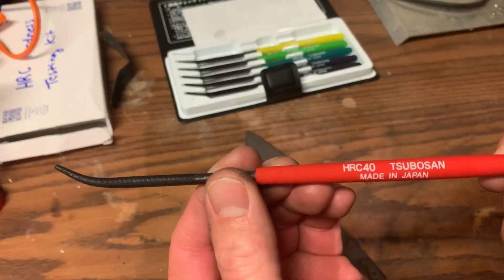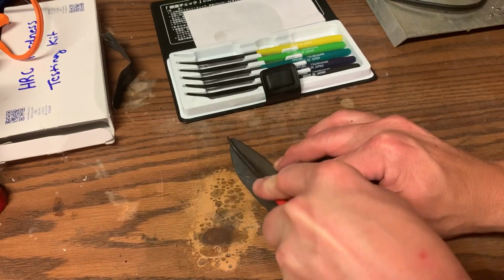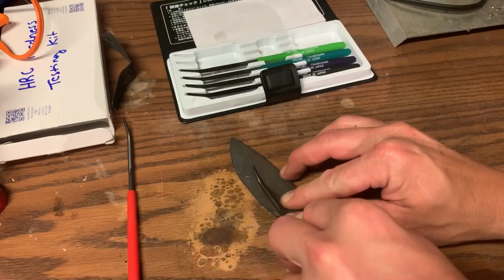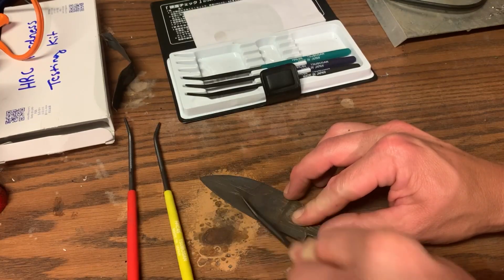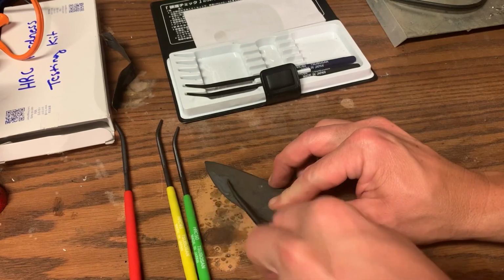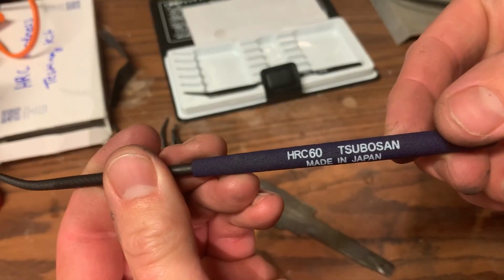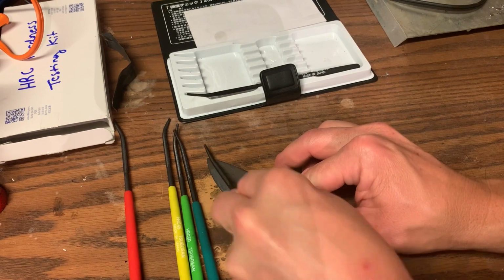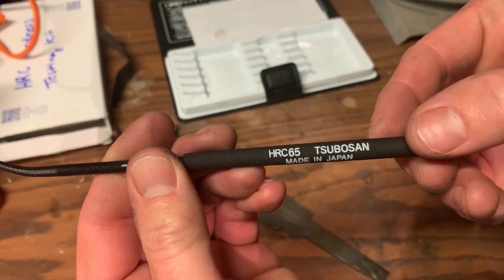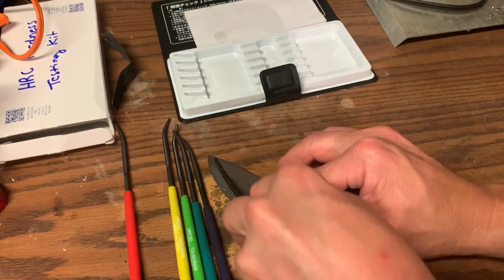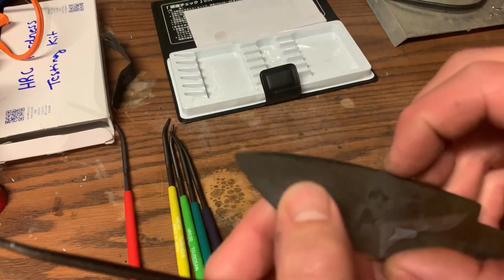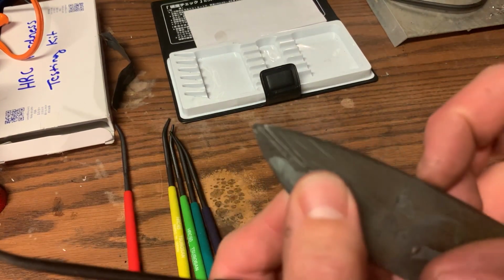Speaking of hardness, I must admit I was very pleased when it came time to test our HRC. As you'll see here, the first file to bite down was the HRC 65, making the HRC an estimated 61 to 62. I find it hard to believe that 431 could achieve anything over 60, but the carbon contents referenced in Part 1 come with a disclaimer that they can vary. All I can say is this particular golf club must have had a delightfully high carbon content, and that plate quenching and deep chill are popular for a reason.